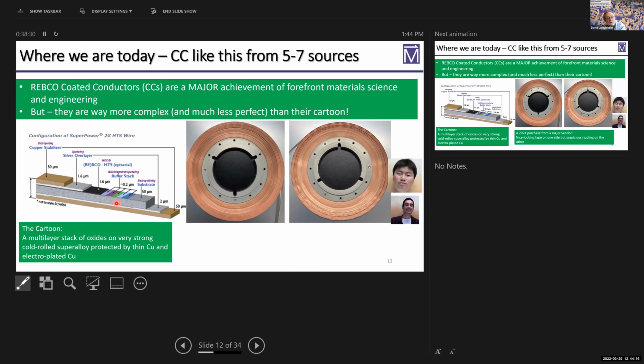It's, however, not protective of nickel diffusing out, and so you put down here lanthanum manganate. And then finally, you have a substrate. All of this is done at room temperature, where you can now grow yttrium barium copper oxide in situ in various ways: pulsed laser deposition, magnetron sputtering, MOCVD.